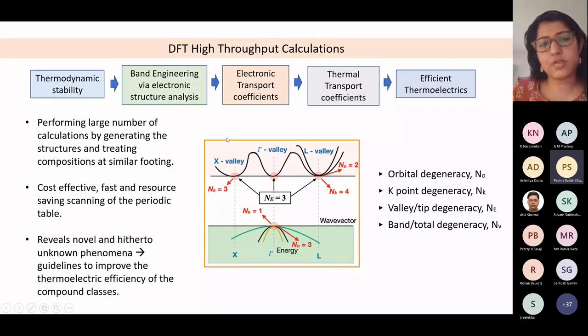In this case, we are showing only the band engineering concept, where we are looking into the electronic structure. So this is a schematic situation shown for a fictitious solid. You can think there are a lot of degeneracies in the bands, in the conduction band. And in principle, all the thermoelectric materials are doped. So if this particular material is N-type doped, and there is a doping limit, and you're coming here, then you can see so many bands are converging. If such a situation can be induced in a material, somehow by doping or substitution of the compounds, then that's a tremendously good situation to look at.